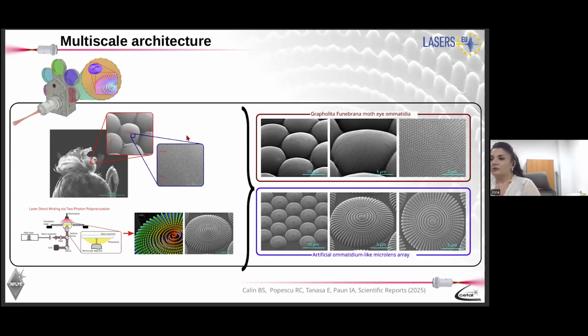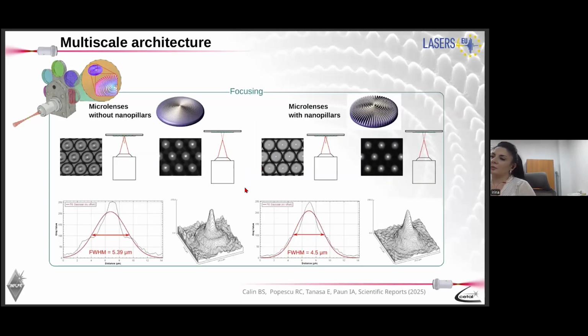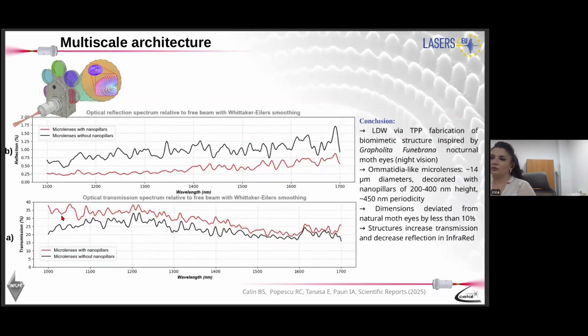We took this example and replicated almost the same structures using our 3D printing technique. We obtained these structures. Here are the natural ones, and here are the ones that we obtained by laser. We tested their optical properties, a little bit the focusing. I will not stay too much here. Also, as I told you in the beginning of this idea, the reflectivity decreased and the transmission increased. So the functionality in the infrared, the functionality of our structures, was validated.